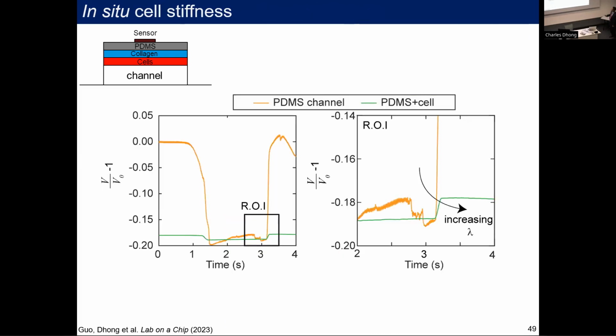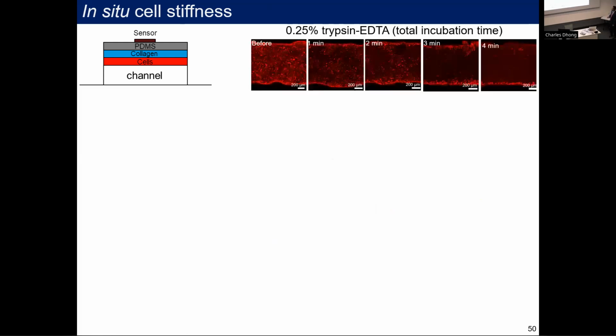So what we can do is then flow a bubble inside. We flow a bubble and you get the signal. And then this bit over here is the viscoelastic relaxation. So we can compare a bare channel to a channel with cells. And when you do that, we can start to get viscoelastic constants of the actual cells themselves, right? So we just add that additional layer, and any change in signal should be coming from the cells. What's great about this is all we need to do is flow a bubble.